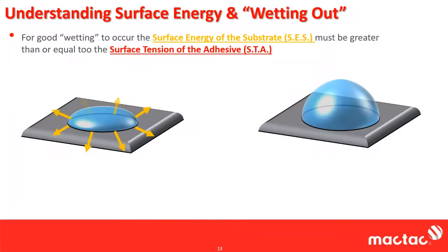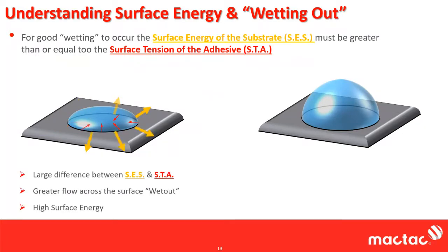So again, looking at the example on the left, we have the surface energy of the material pulling against the adhesive bead, and the surface tension trying to hold it in. In this example, there's a large difference between the surface energy of the substrate versus the surface tension of the adhesive. The result of that is you have greater flow across the surface, or you get wet out. Look at how low that bead is. It's covering a larger area of that substrate. The substrate is pulling on it much harder than the surface tension is able to hold it in place. That is a high surface energy material.